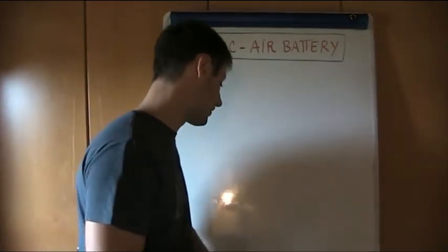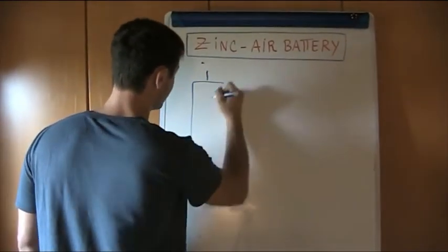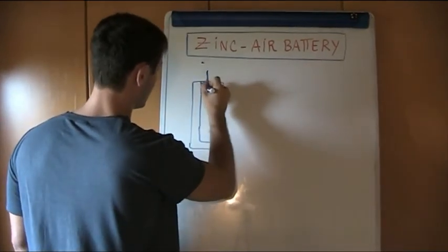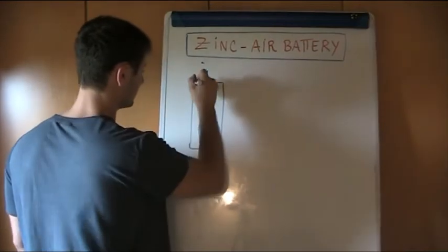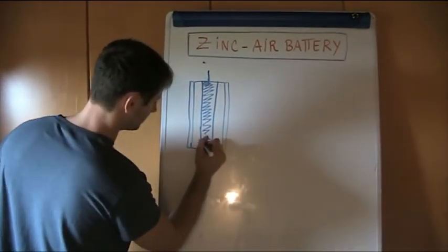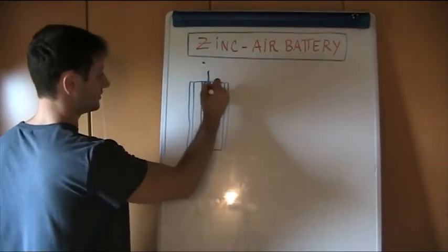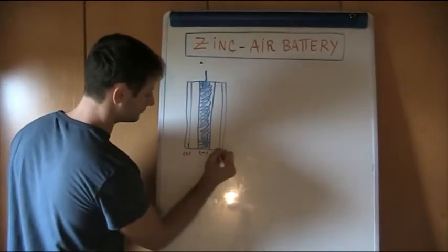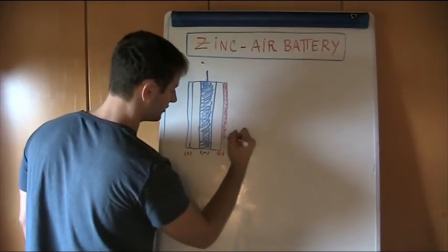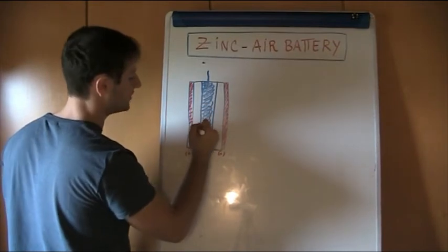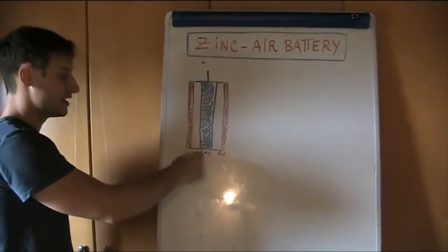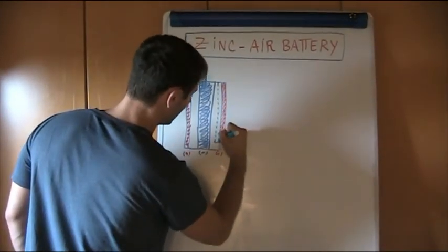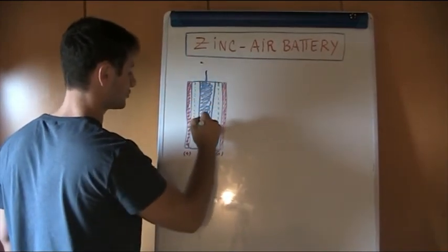What does it mean? If we look at particular types of zinc-air battery design, we can have, for instance, a single metallic zinc electrode, which is the negative electrode, the one that is colored, in which zinc oxidation is occurring, and two different cathodes, two different positive electrodes in which oxygen reduction is proceeding. Nothing different with respect to the previous situation, but in this case we have only one negative electrode and two positive electrodes, separated by an ion-permeable but not electron-conductive membrane.